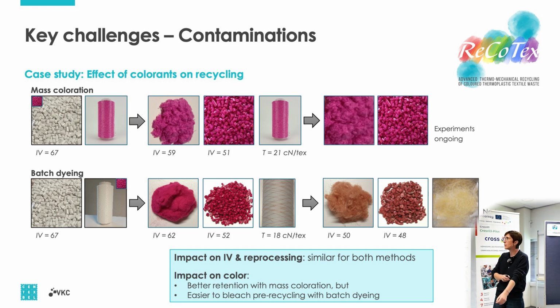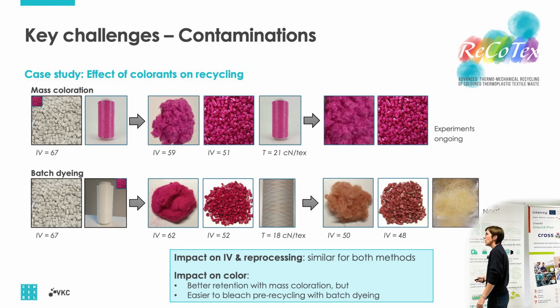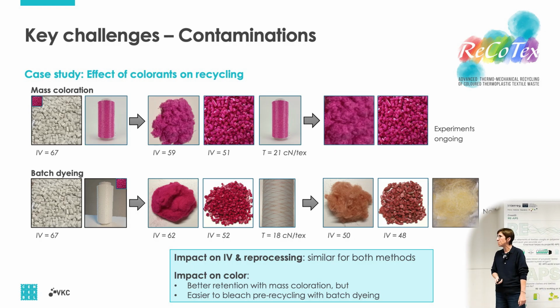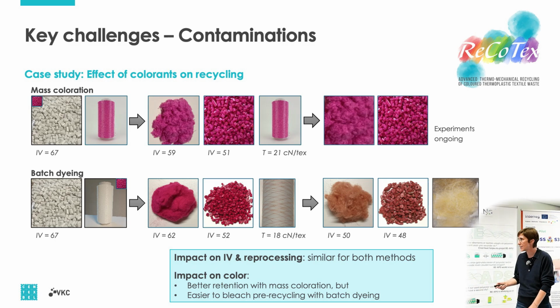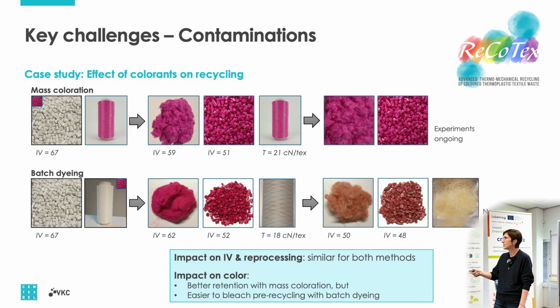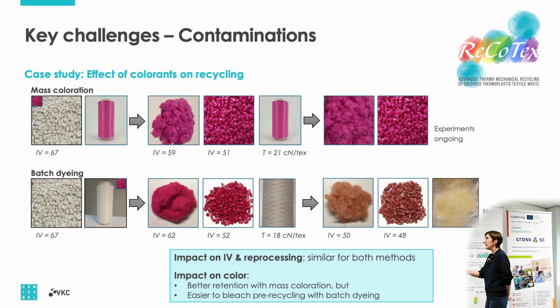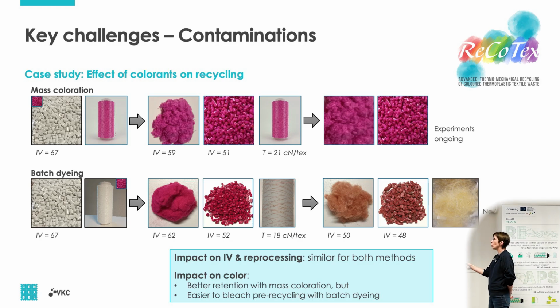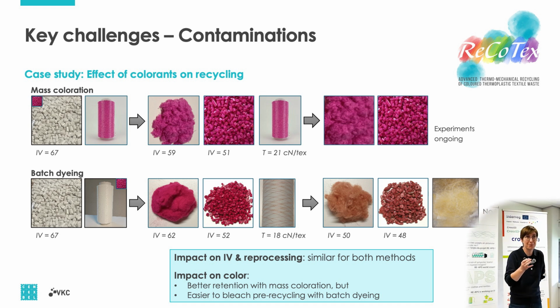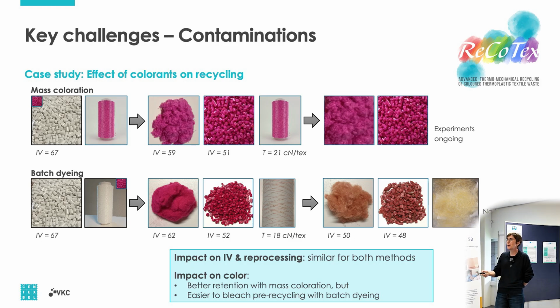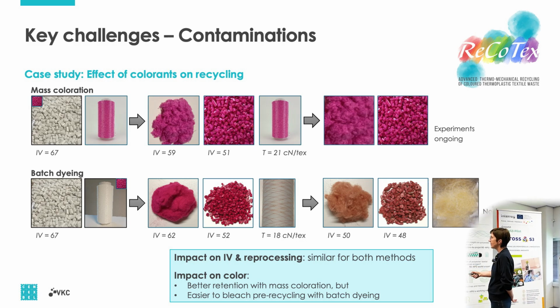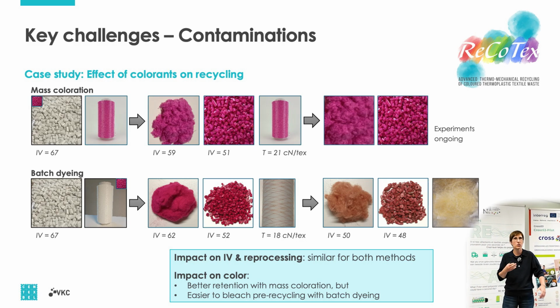Another example, from a project we are running at the moment, where we try to evaluate the difference between something that's mass colored, so you add something into your polymer matrix, and a batch dyed material, and then we try to process it into different recycling routes. First important thing that you can see: if you have something that's mass colored, you keep your color quite well. If you have something that is batch dyed and you try to reprocess it, we are losing some of the coloring, and even after a certain loop, the colors completely change. So yes, this could maybe be a way to remove color from something batch dyed, but to be honest, we also lose a lot of properties. So is this still processable? No, because in the end we didn't have any bobbin left anymore, it was too unstable, so we had a lot of contamination.